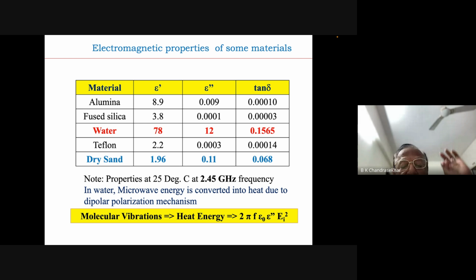Very slowly they will increase the temperature, so that the differential temperature is minimal, but then it takes 2 to 3 days to dry it. But with microwave, the whole thing can be done very fast, because the surface as well as the inside are dried at the same rate. So the important thing is the total amount of energy available as heat basically depends on the frequency, the epsilon double prime, which is the loss factor, and the electric field.